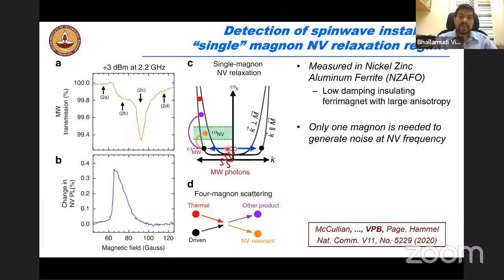And both of these are related to instabilities that we are creating. So we are creating some Suhl instabilities, these are basically high power regimes. So we are doing some parametric excitations of high K magnons. And so these are two magnon processes that can give you basically high K, these non-zero K magnons. And those are what are now being scattered. And that is what is giving us this. So those are being scattered to be resonant with the NV centers.